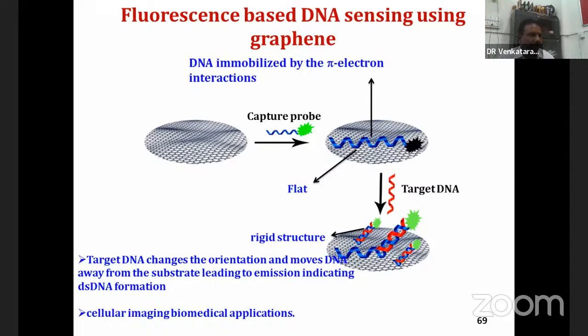In other words, if you do the reverse, for example, if you have a single-strand DNA and you label it, and you have only single strand, you get no signal without the label. If I have a labeled target, once it reacts, it will give a fluorescence, and you have to wash it. If you wash it, the unreacted DNA will go away. If there is no reaction, the fluorescent signal will not reoccur. So based on this, they have developed an on and off sensor device which indicates the presence of single strand or the double helical structure.